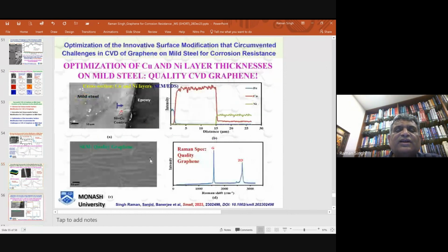So what we did, that we took into account the time temperature window, how long it will take for mild steel or copper to diffuse through the nickel layer to come to the surface. And accordingly, we decided the thickness of copper layer and nickel layer. And that was about 10 to 12 micron of copper layer and 10 to 12 micron of nickel layer. And we developed that kind of optimized layer. And then we could develop very good quality graphene. You can see no defects. G peak is taller than 2D peak, is multi-layer graphene, and that gave us very, very good corrosion resistance.